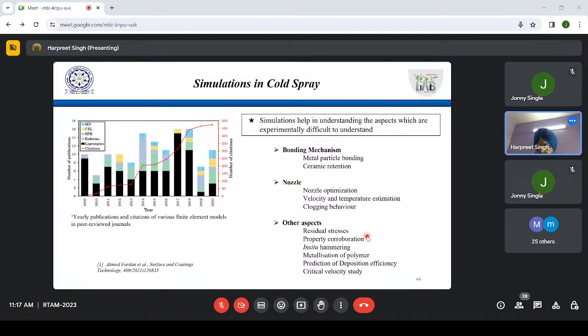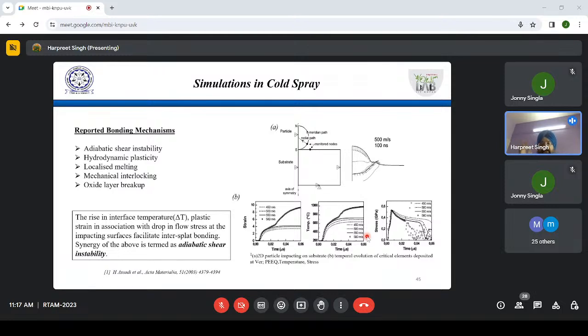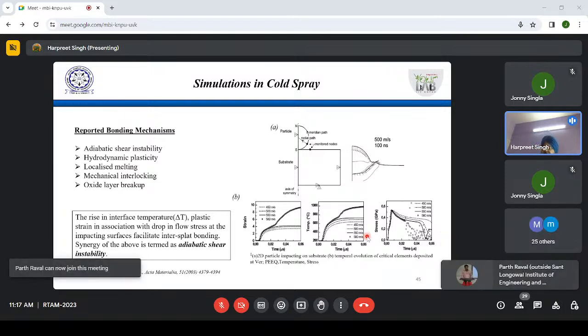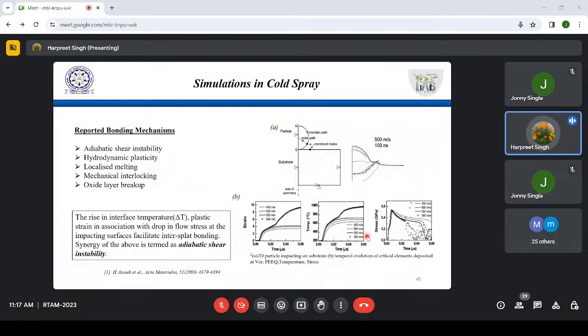These are helpful, and in my opinion, they will help us on one side to understand the process. On the other side, they will give us economical use of cold spray also. For example, as I told you in the beginning itself, it sometimes becomes very difficult whenever I get a new combination of materials to be deposited or processed through cold spray. The challenge becomes at what parameters we should start, right? And if I go randomly, I will be spending a lot of gas to arrive at the optimized parameters, right? But now we have some models which are very nice to predict those process windows for these unknown materials, right? So that is where I would say that there is a lot to be understood through simulations also,